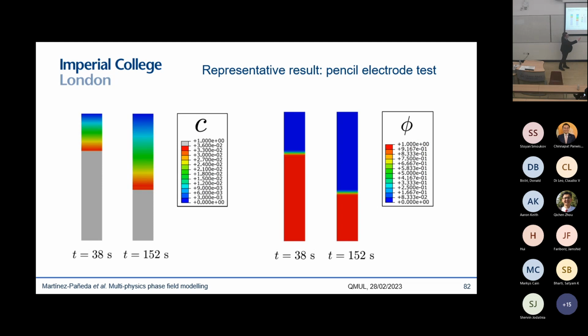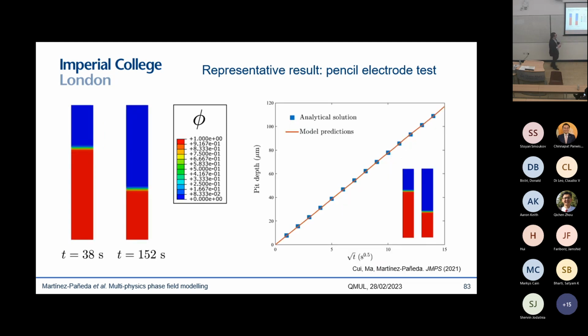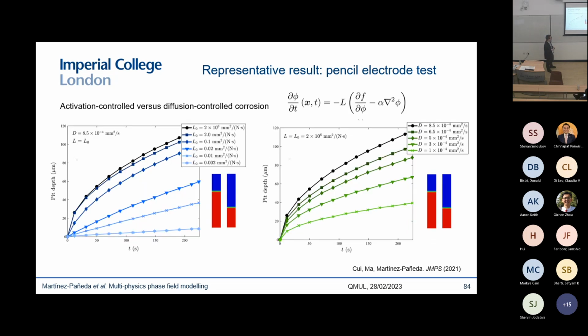So you can see with time how the corrosion front is evolving, and you can see the distribution of metal ions away from the corrosion front. And basically, this is a good example to validate the model with analytical solutions for the case of diffusion-controlled corrosion, because this is a 1D example, and also to show that the model can naturally capture the interplay between activation control corrosion and diffusion control corrosion. So the model depends on only two parameters, essentially.